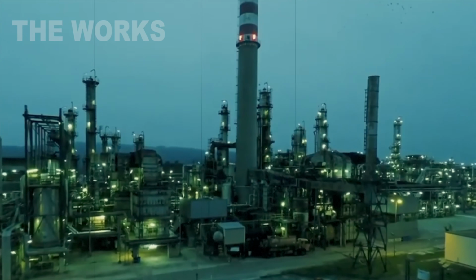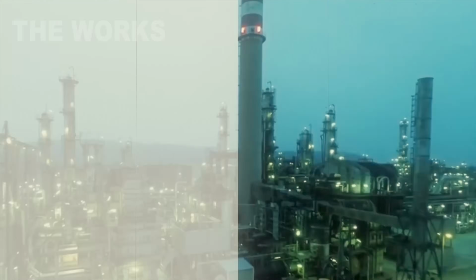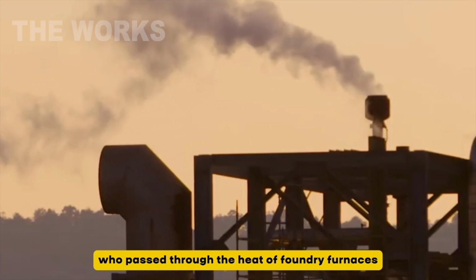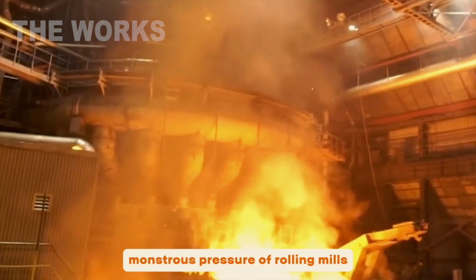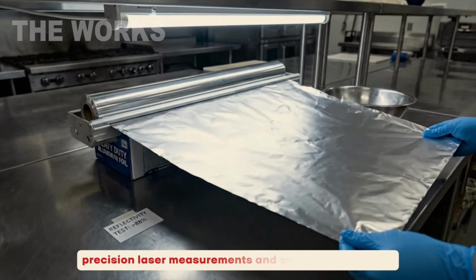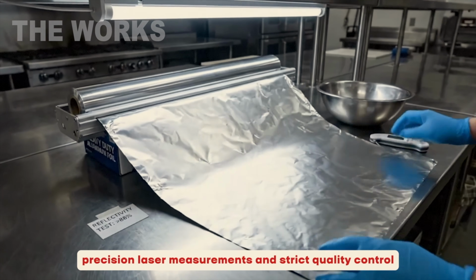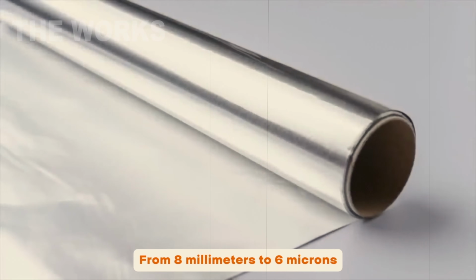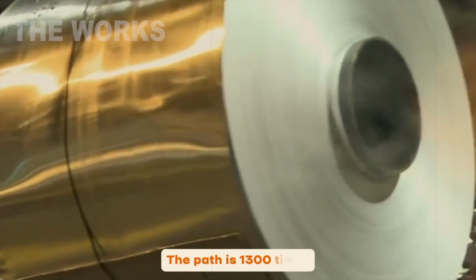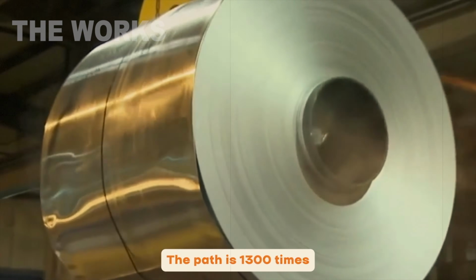This entire foil empire was born from a simple piece of aluminum that passed through the inferno of casting furnaces, the monstrous pressure of rolling mills, the precision of laser measurements, and rigorous quality control. From 8 millimeters down to 6 microns, a journey 1,300 times over.